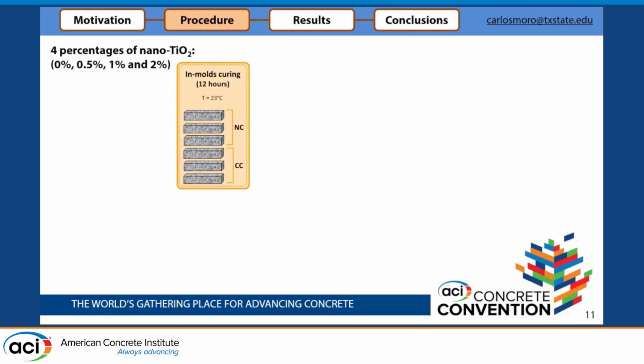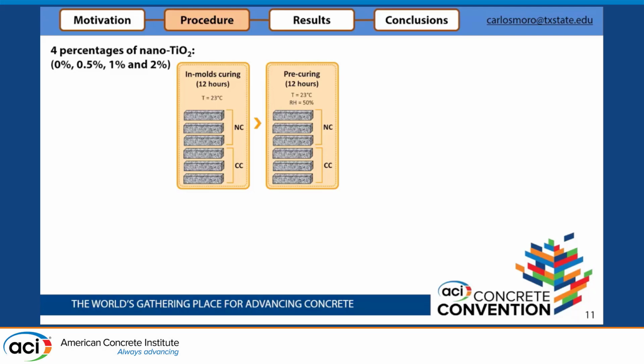So in order to test this hypothesis, we made 4 different mortars, 4 different cement pastes, sorry, with 4 percentages of nanotitanium dioxide from 0 to 2%. We first cured the molds for only 12 hours, and then we pre-cured them for 12 more hours, because when we tested before just removing them from the molds and putting them in the carbonation chamber, the humidity was so high that the efficiency of the CO2 capture was not that much. So we decided to do a pre-curing with a 50% humidity as a preconditioning in order to improve the efficiency of this CO2 capture.